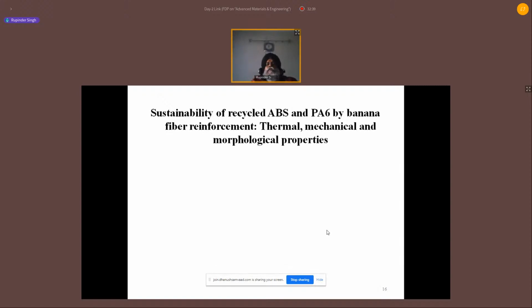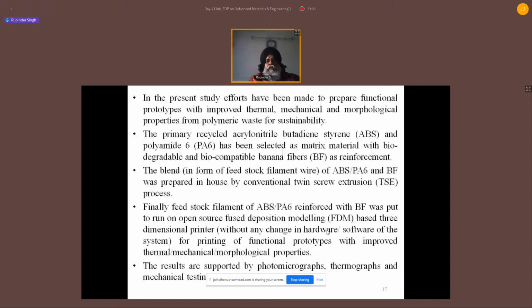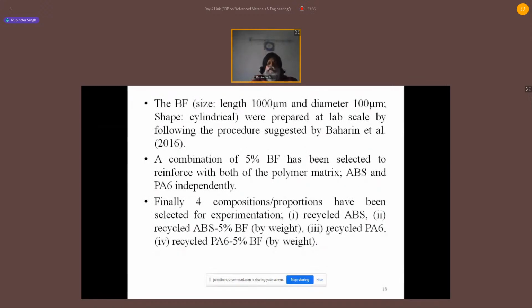So once we were developing the feedstock filament at our end, one of our suppliers was from Jalgaon, and he told us that at that place there is a lot of banana production, and the banana fibers are available at very low cost. So we tried to reinforce those banana fibers in ABS and PA6, and we got a really wonderful result for the 3D printed parts. For this particular case, we used banana fibers of 1000 micron length and 100 micron diameter. There is a very good paper by Baharin et al., where the authors have reported how to condition these types of banana fiber for different types of reinforcement.